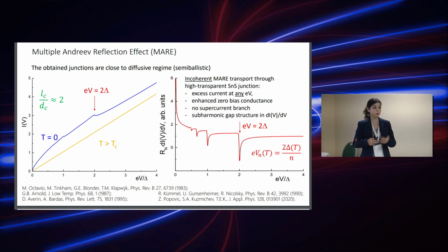Using the mechanical readjustment, we could vary the contact resistance and transparency. And also typical features of the materials matter, so the Josephson characteristics are typical, but in iron-based superconductors we obtain only Andreev ones. It depends on the contact transparency. The Josephson regime corresponds to extremely low transparency. And here the transparency is extremely high, more than 90%, maybe.